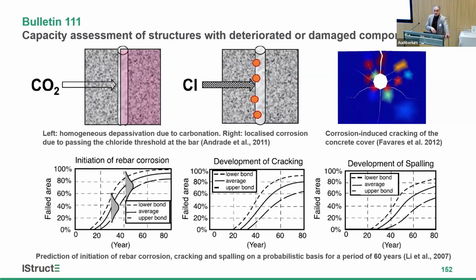It's either carbonation-induced corrosion or chloride-induced corrosion. Carbonation-induced corrosion is essentially the concrete cover reacting with the CO2 in the air. In the UK, we don't have that much problem with the CO2 or with the carbonation. What we have in the UK is mainly chloride-induced corrosion.